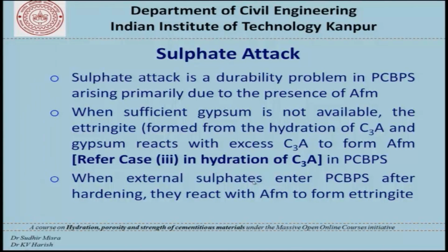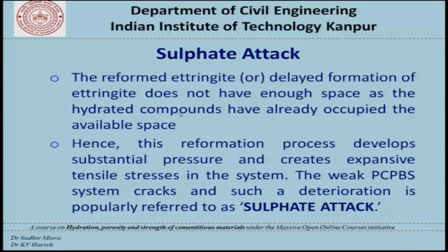When external sulfates enter PCBPS after hardening, they react with AFM to form ettringite. The reformed ettringite or delayed formation of ettringite does not have enough space as the hydrated compounds have already occupied the available space. Hence, this reformation process develops substantial pressure and creates expansive tensile stresses in the system. The weak PCBPS system basically cracks, and such a deterioration is very popularly referred to as sulphate attack.